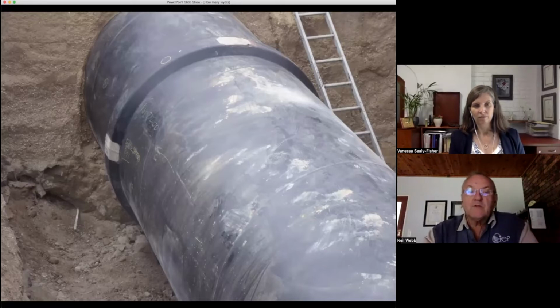In this situation, the pipe is blast cleaned to provide a rough surface, which gives you mechanical adhesion. And then the pipe is heated, and the pipe is dipped into a fluidized bed of polyethylene powder. The powder then sticks to the pipe surface, it fuses and forms a coating, which is a couple of millimeters thick, and you'll end up with this sintered polyethylene coating, which is then secured to the pipe purely by mechanical interlocking between the polyethylene and the rough surface of the pipe.